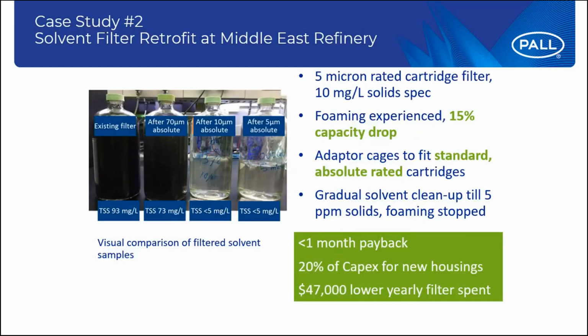A case study for a customer that had a filter not specified as an absolute filter, so clearly it was a nominal filter. The specification was to have a 5 micron rated filter. Well, the customer had it, but the spec to meet 10 milligram per liter is clearly not the case, because as you can see on the sample on the left side, TSS, total suspended solids, was 93 milligram per liter, and the customer was experiencing foaming.